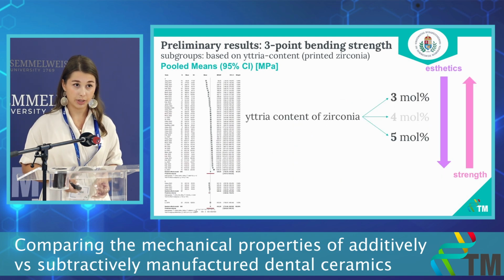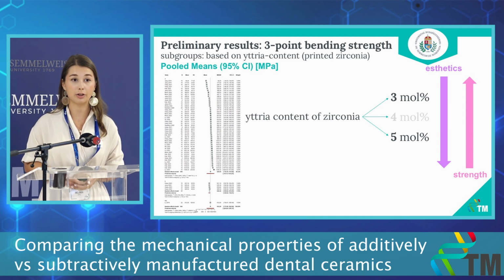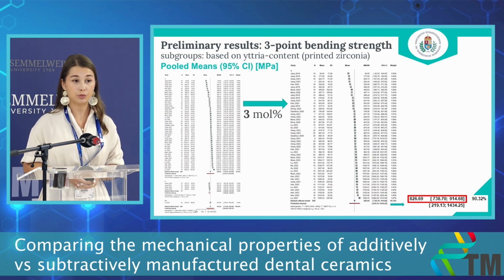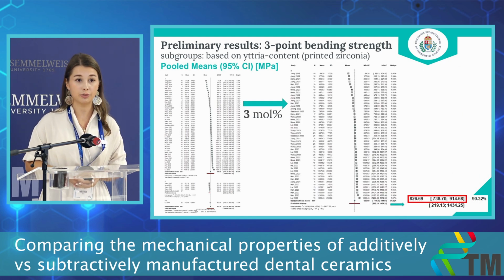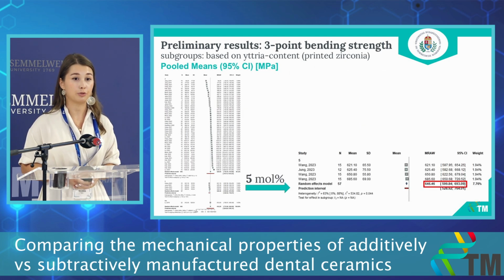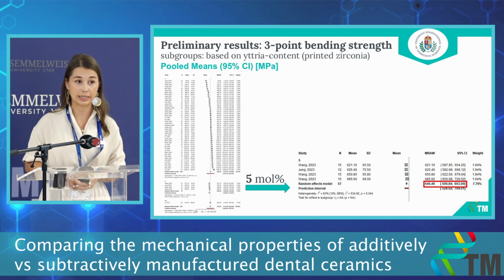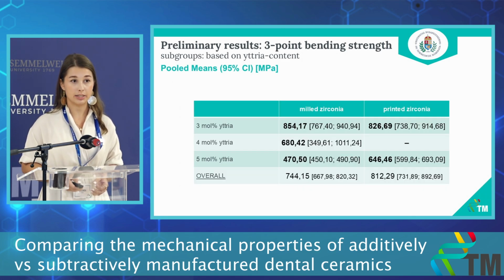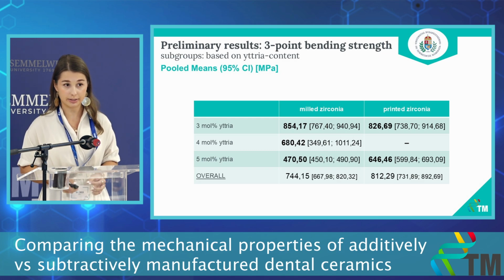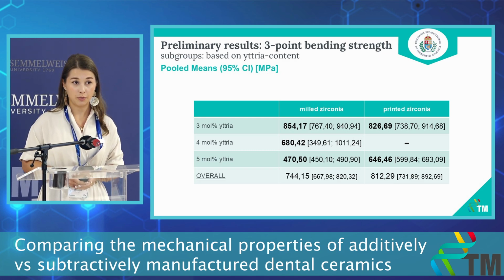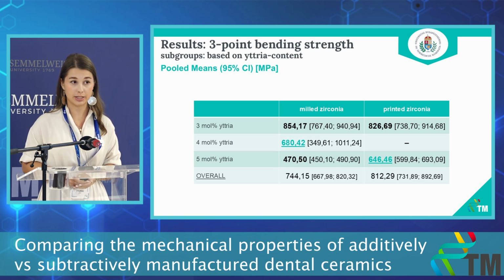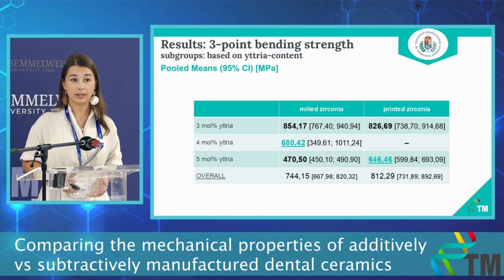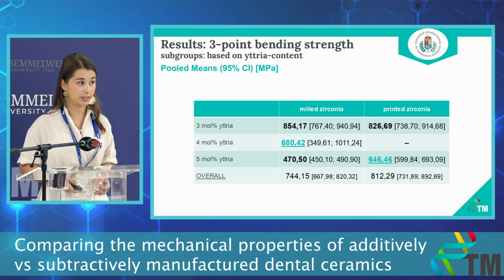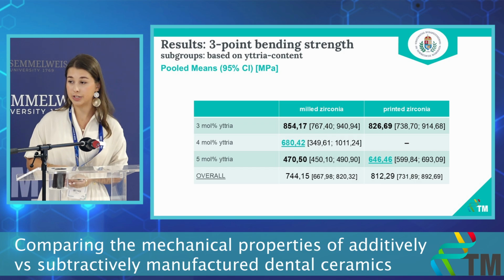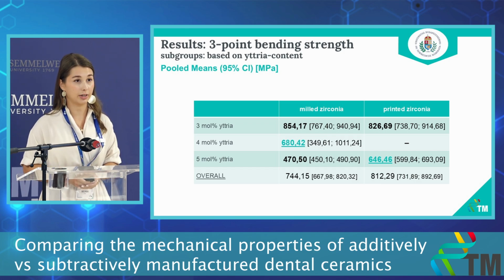Looking at printed zirconia, we can see the same pattern, with the only difference that there is no 4% yttria stabilized zirconia available for printing yet. So with 3% yttria, we have an overall flexural strength of 826 megapascals, and with 5%, it is only 646. What is really interesting is if you look at the 5% yttria stabilized zirconia in the printed group, we have similar flexural strength as the 4% yttria stabilized zirconia in the milled group, meaning that with 5% yttria stabilized printed zirconia, we can get really good aesthetical results without compromising for lower flexural strength.